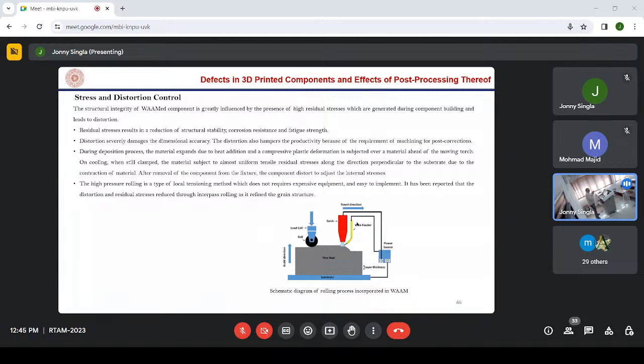Second is the stress and distortion control. Stress and distortion due to residual stresses is also a very important issue in case of WAAM. Residual stresses result in a reduction of structural stability, corrosion resistance, and fatigue strength. Distortion severely damages the dimensional accuracy. The distortion also hampers the productivity because of the requirement of machining for post corrections. During the deposition process, the material expands due to heat addition and a compressive plastic deformation is subjected.